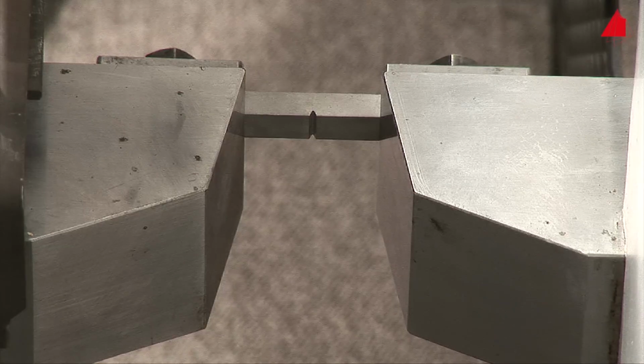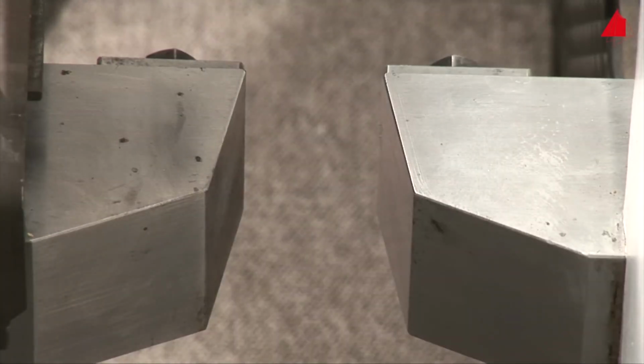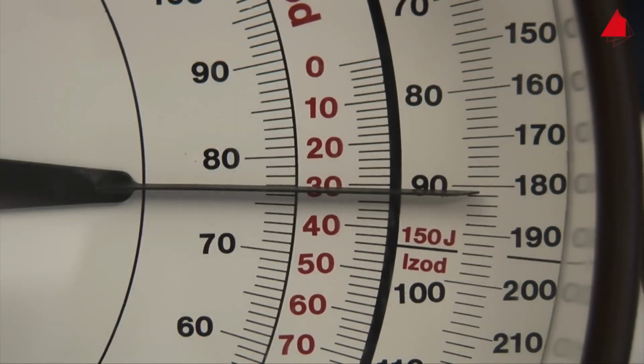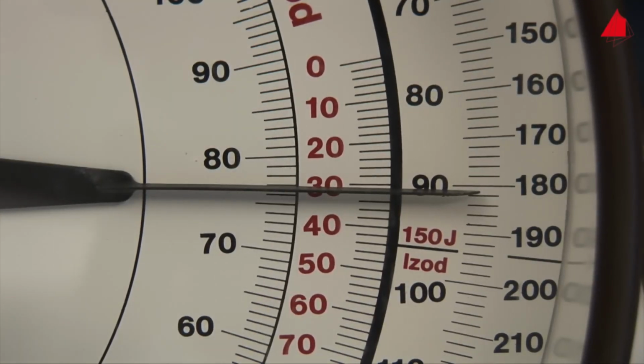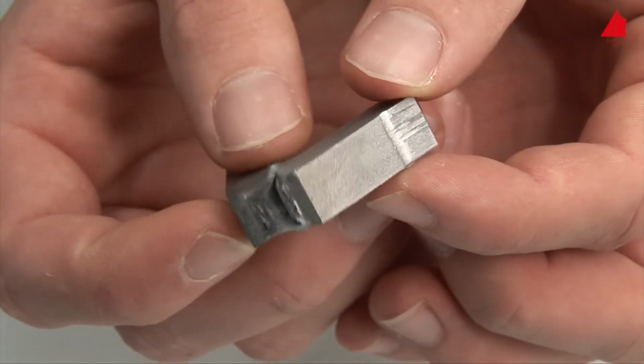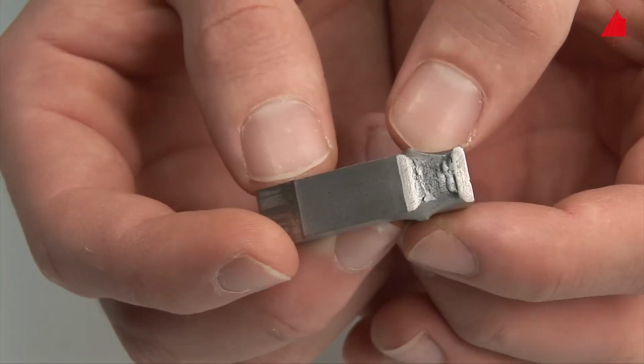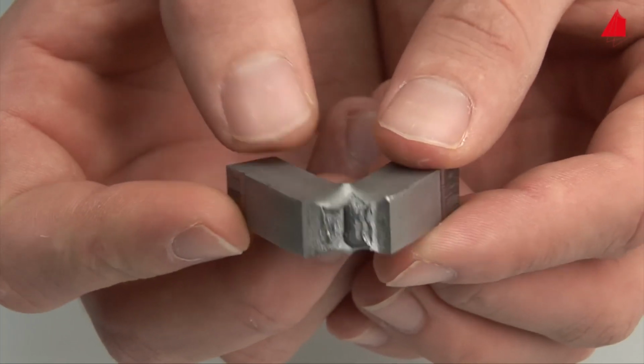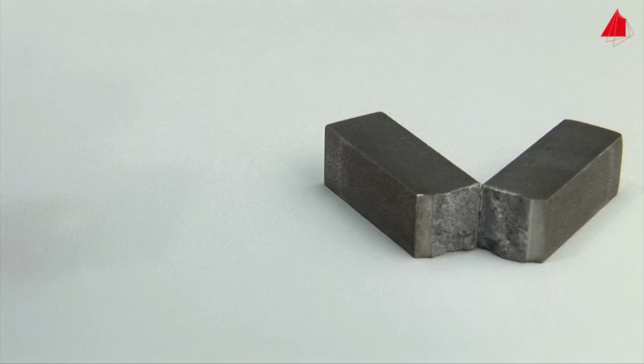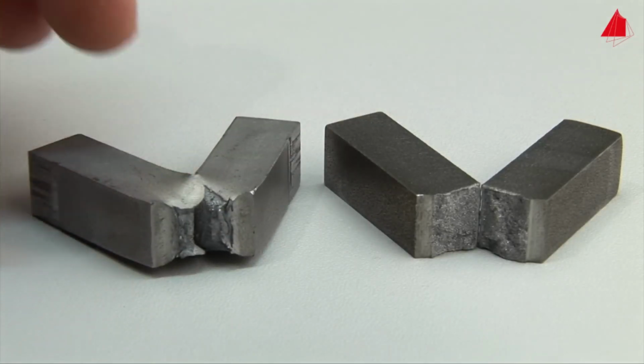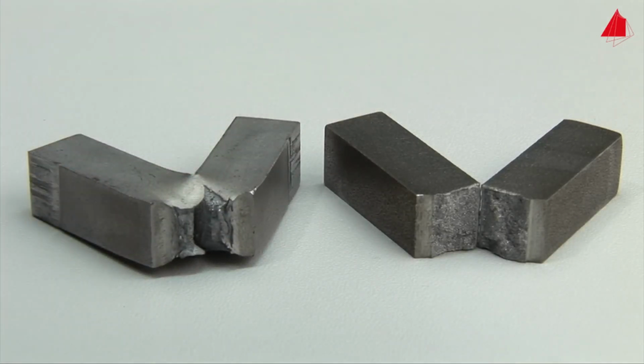This time the impact sounds much deeper and richer. An impressive energy of 182 joules has been absorbed by the specimen. Here the specimen did not break into two pieces. Instead it was pushed through the counter bearings under heavy plastic deformation. In comparison with the strain-aged steel, the normalised steel absorbs much more notch impact energy and behaves in a very tough manner.